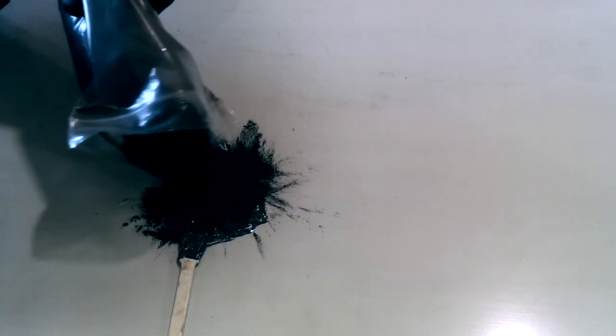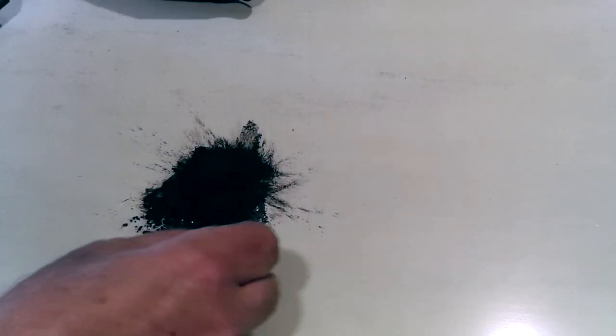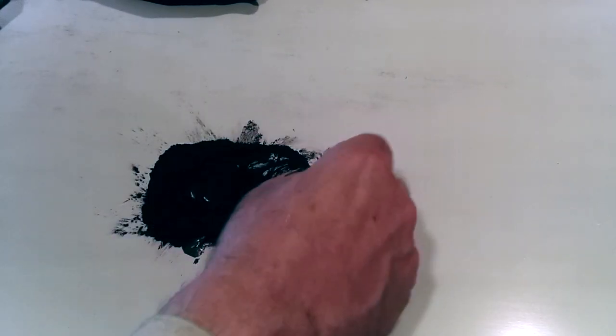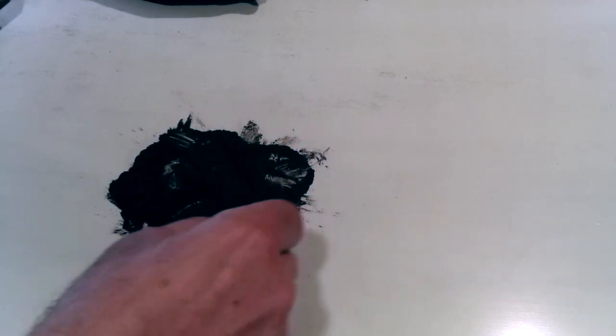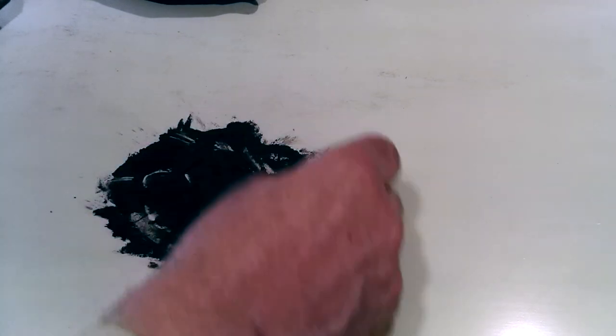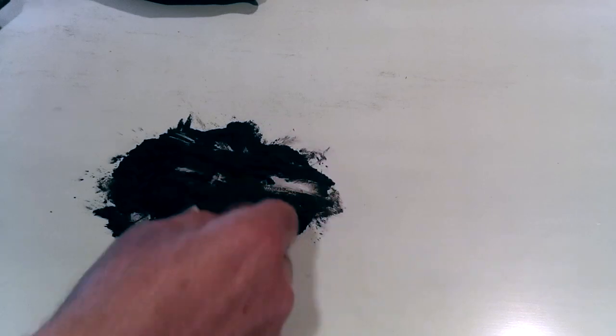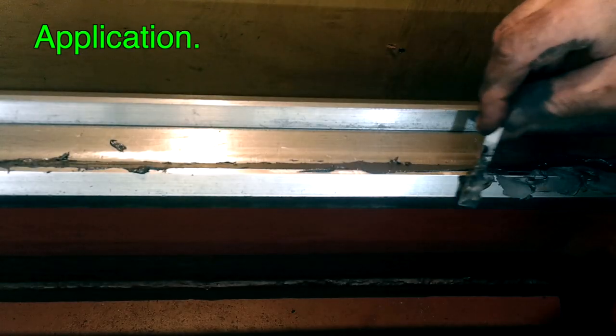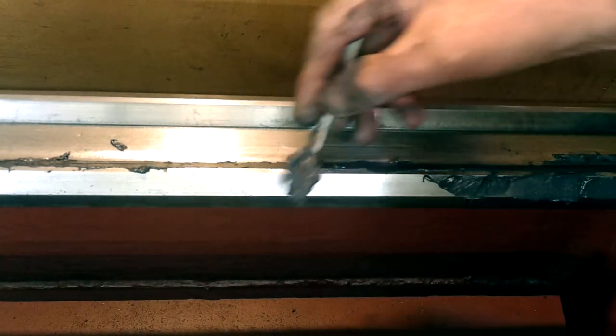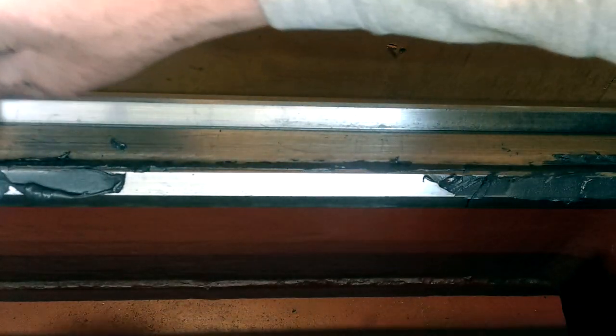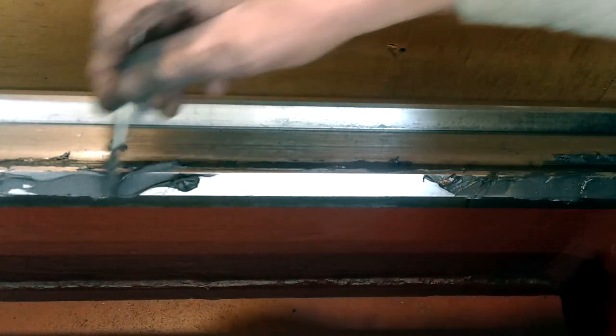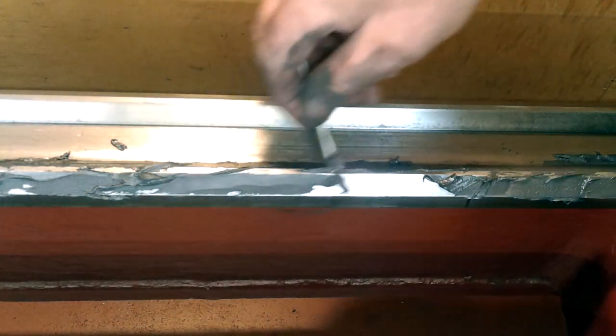At this point I started to mix the iron dust into the resin. I could only guess at the amount of resin that I needed for this particular mix. So I used one tube of resin and one of the hardener with about a spoonful of iron powder. Laying the resin mix onto the V-ways was only hampered by the small and inadequate size of the spatula. Working the mix was a bit like laying a very grainy body filler. The mix did its best to stick to absolutely anything it touched.